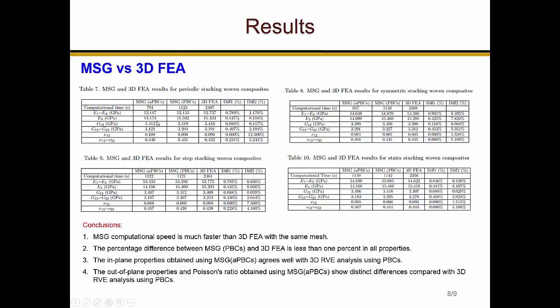And MSG can also do the periodic boundary conditions, which has been introduced in the last video. And it is easy to perform. And I will not show this function in this video. And if you perform the MSG periodic boundary condition by yourself, you will find some interesting behavior of this layered shift or interplay shift problems. That you can see the in-plane properties of the four configurations are almost the same. But the out-of-plane properties and the Poisson's ratio has a relatively big difference between the 3D FEA analysis.